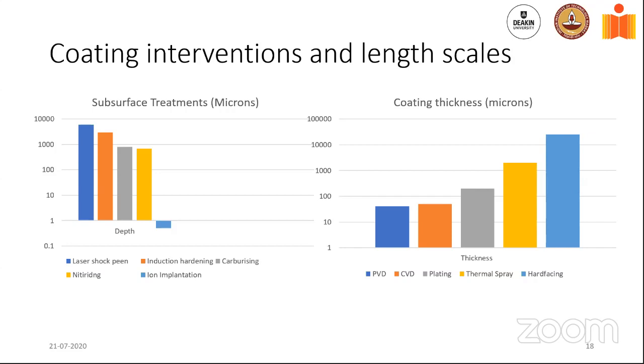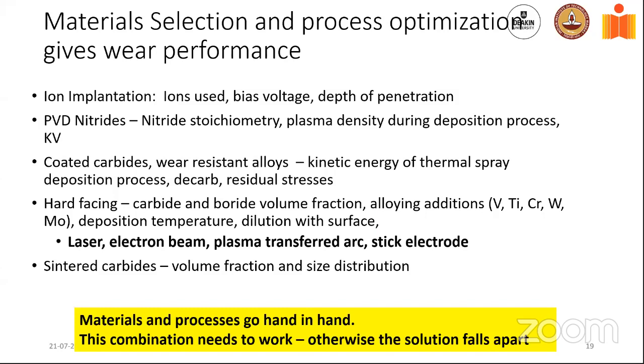The PVD ends up at around 30 to 40 microns max, 2 to 3 microns typical. The CVD ends up at around 10 to 20 microns typical. The plating is 50 to 100 microns typical. So you do a lot of things at that length scale to essentially change the component surface. Right. So I'm going to lead into essentially additive manufacturing here.